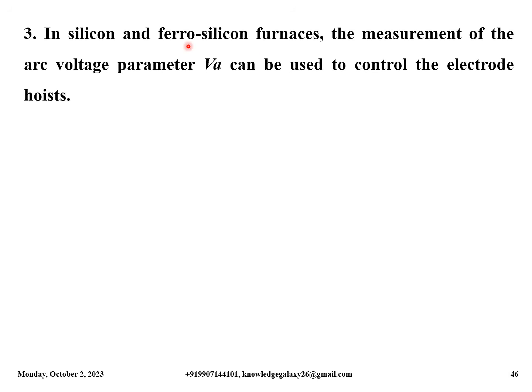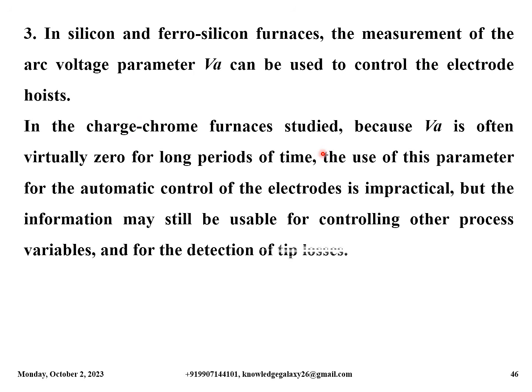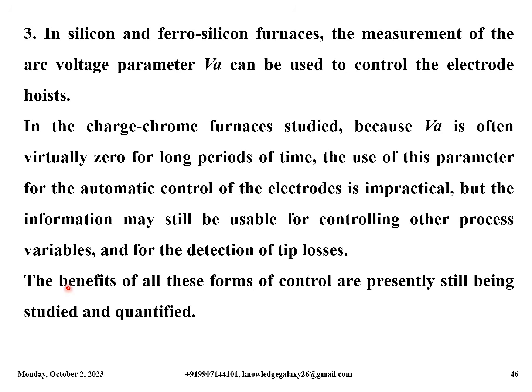Third point, in silicon and ferrosilicon furnaces, the measurement of the arc voltage parameter, that is VA, can be used to control the electrode hoists. In the charge-chrome furnaces studied, because VA is often virtually zero for long periods of time, the use of this parameter for the automatic control of the electrodes is impractical, but the information may still be usable for controlling other process variables and for the detection of tip losses. The benefits of all these forms of control are presently still being studied and quantified.